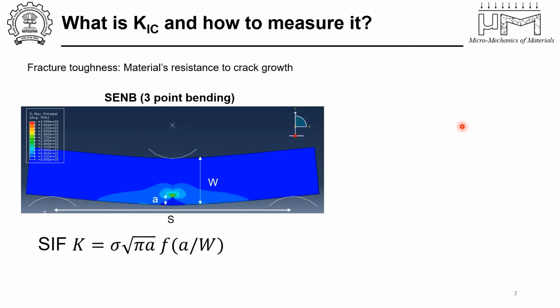So before I begin, I do not know the particular audience, so just to give a short introduction of what we are looking at. So what we measure is the driving force for crack growth. So you have, let's say, a rectangular beam, and you have an initial crack that you make in the sample, and you load it in, for example, a 3-point bending configuration. Then what you would obtain is the far field applied stress that is applied on the material and the crack length that is already there in the sample, the combination of which will give you what is called the stress intensity factor.